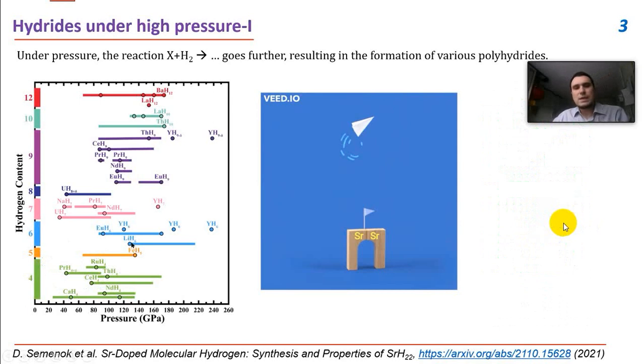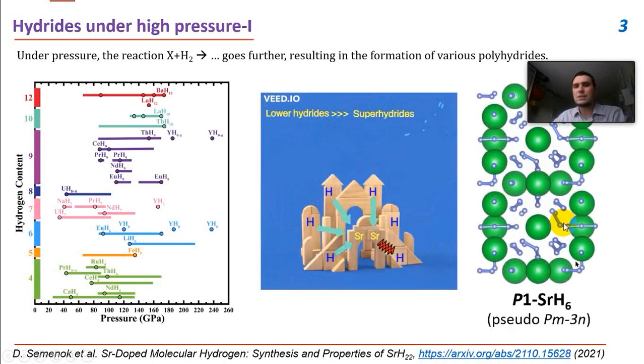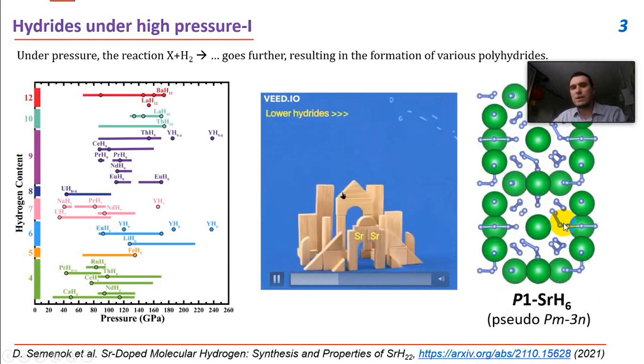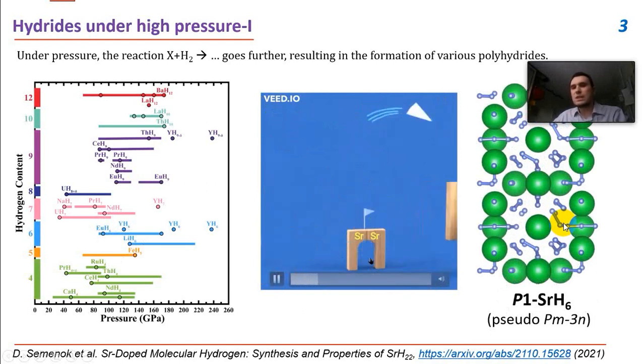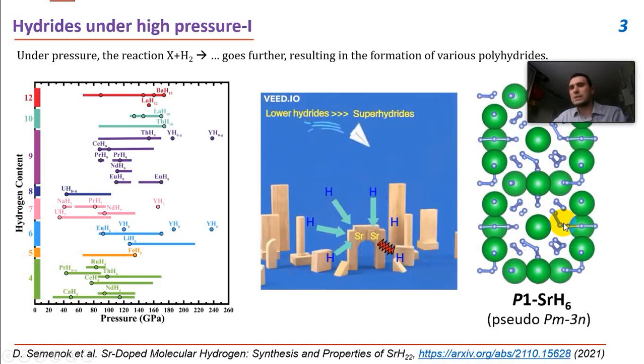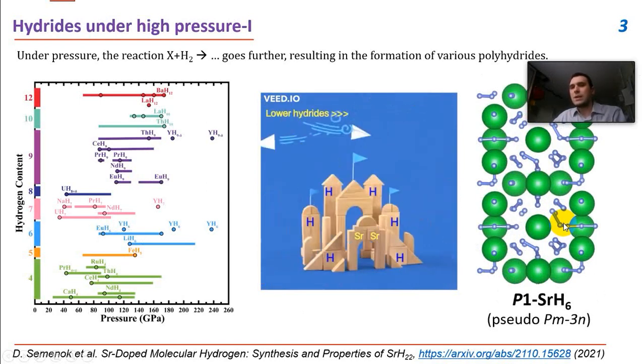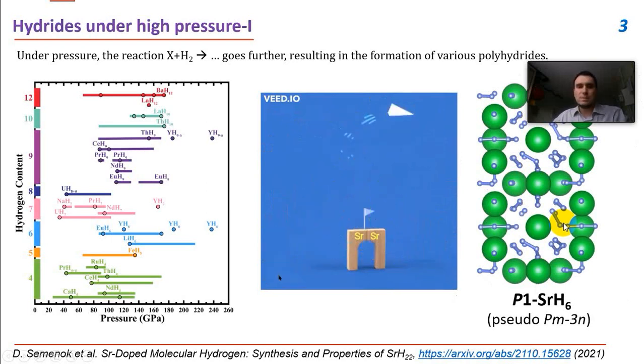When we increase the amount of hydrogen, we can get hexahydrides such as yttrium H6, europium H6, lithium H6, and even, in our recent work, strontium H6, where molecules of hydrogen assemble together in the unit cell with strontium atoms. They interact and form such a molecular compound. It's a yellow-colored semiconductor, which was described in our recent publication in 2021.